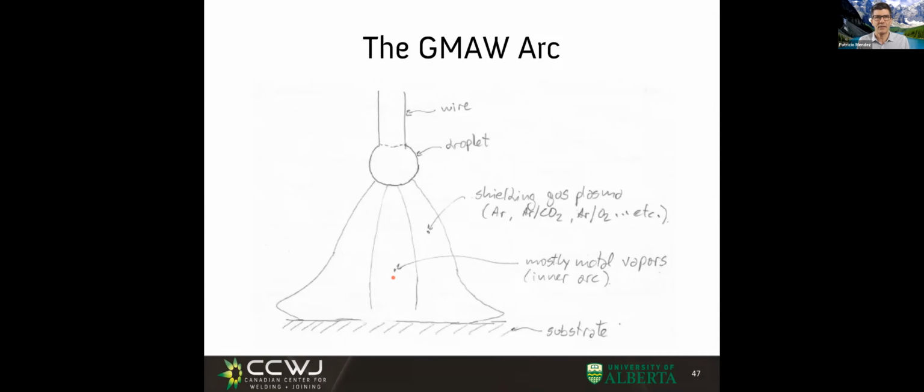If you neglect the phase transformations in the solid, your calculations are more or less the same. If you neglect melting temperature, you're a little bit off, but not a whole lot off. But right now, I'm focusing only on what happens in the arc, and we'll discuss electrode and plate later on.